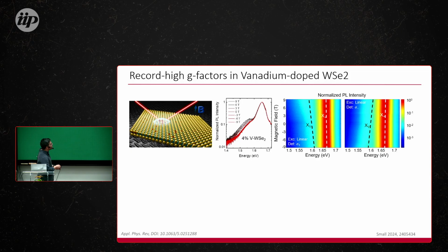And in the lower range of energy here, about 1.6, we see some shoulders, right? These shoulders are defect states. So basically it means that we are trapping the excitons in those defects. And where exactly is this defect? It is the impurity that I'm replacing.